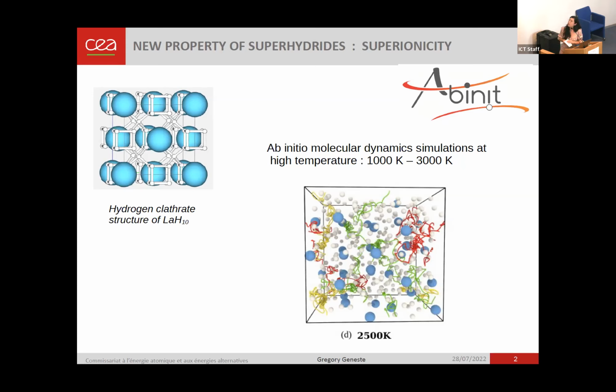So we show here another remarkable property for superhydrides, which is superionicity, hydride superionicity in LaH10 at high temperatures. For this, we launched ab initio molecular dynamics simulations using the code ABINIT at high temperatures between 1000 Kelvin and 3000 Kelvin. Here is an example of the superionicity in the compound LaH10. In blue you have the lanthanum, and in white the hydrogen. We followed the trajectory of 3 hydrogens in green, yellow, and red.